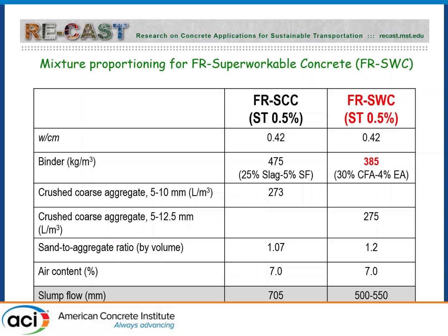So if you were to say 385 kg per cubic meter, that's about 650 pounds per cubic yard. So the mixture is also more robust and tolerates more variability in moisture content of sand or temperature or superplasticizer demand. Otherwise, the difference is that with the SCC, you need a smaller aggregate. So we're using the 3/8-inch aggregate versus the super workable is using half-inch aggregate, and you have more sand. So you reduce the amount of coarse aggregate, you increase the amount of sand to maintain the same mortar content.